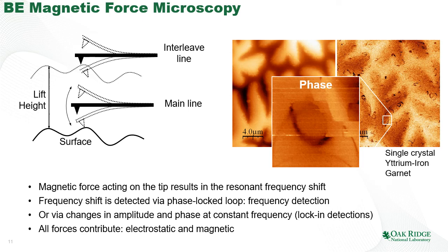Here is an example of the amplitude and phase of the MFM signal above a yttrium iron garnet surface. The surface is absolutely flat — nothing interesting in the surface topography. However, the amplitude and phase show a very beautiful flower-like domain system — classical magnetic domains in garnets. Looking at the phase signal, there are small round objects which are perfectly reproducible. Zooming in on one, we can see some change in the cantilever phase during interaction with the surface. After exploring this issue, we know that the material contains a small number of magnetic dissipation centers where the cantilever falls into micromagnetic resonance and starts to lose energy.